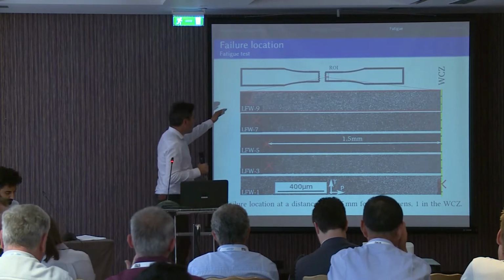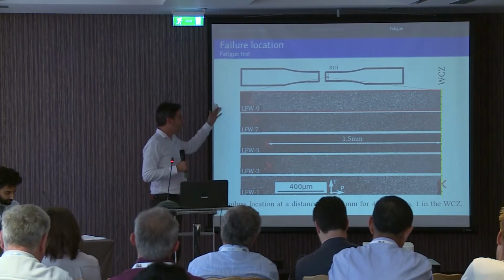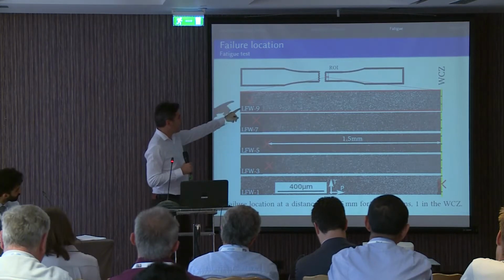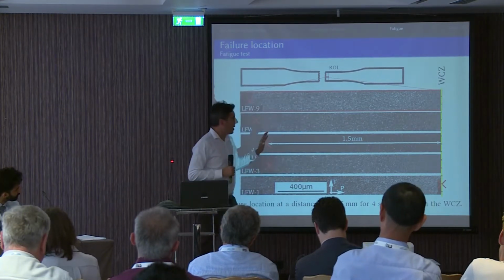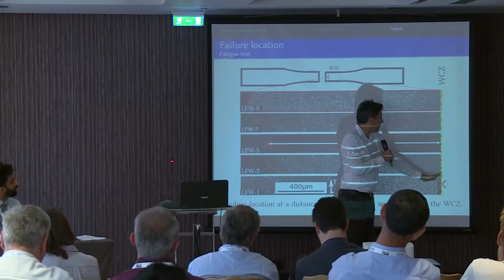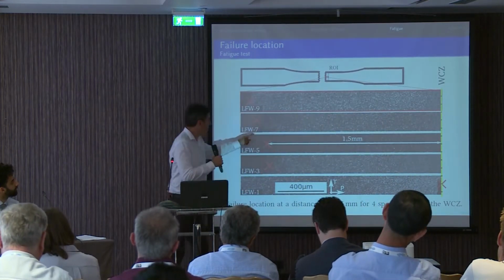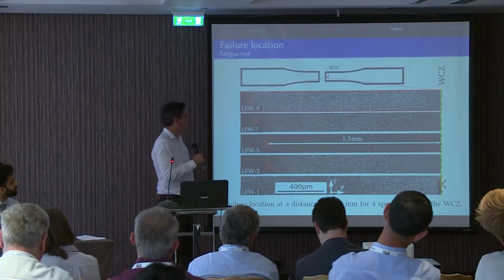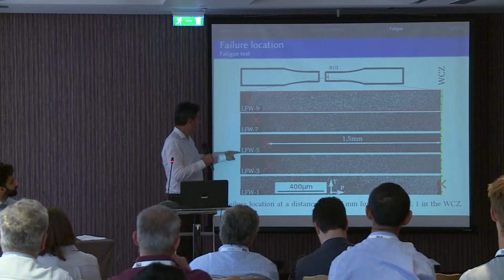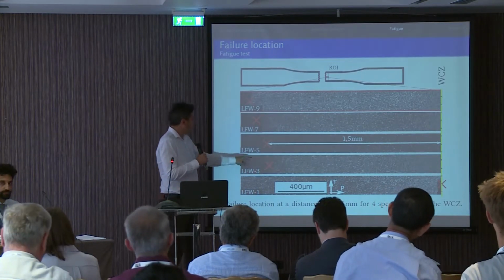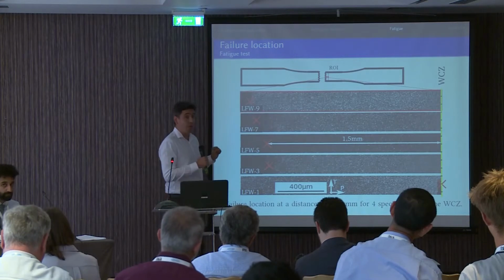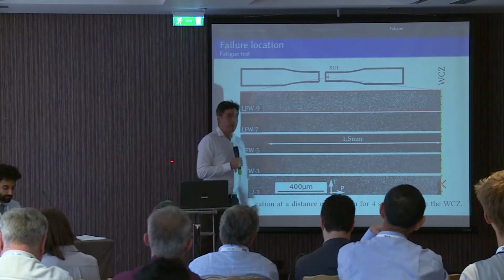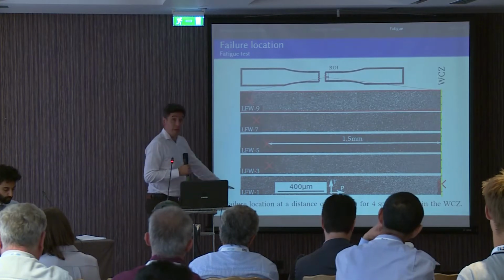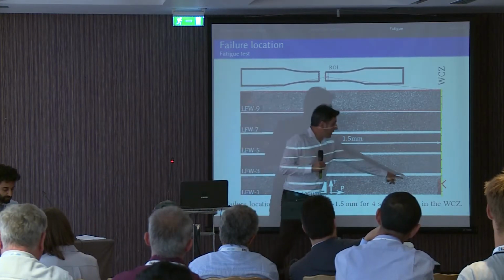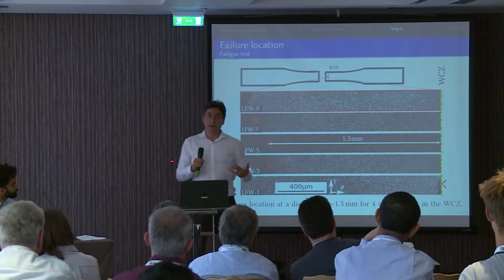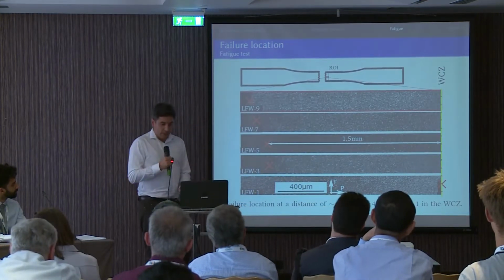So here I'm showing 5 backscatter images of the surface of the specimen. I aligned them with respect to the weld center zone, and the red crosses show the fatigue crack initiation site. For the specimens 9, 7, 5, and 3, failure takes place far away from the weld center zone. In particular, it's 1.5 millimeters more or less. And the one that has a short life fails in the weld center zone. So we have 2 different localizations.